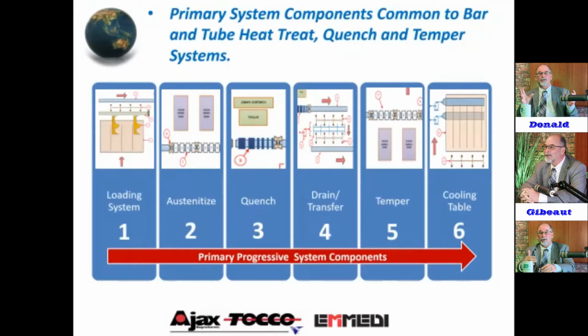First is your loading system, then the austenitizing section that brings it up to somewhere between 1650 and 1850 Fahrenheit. And then we go into a dynamic quench that is controlled by the TTT curve. You've got to knock it down, typically under 10 seconds from that temperature, from the surface to the core, uniform, to get the uniform metallurgy.